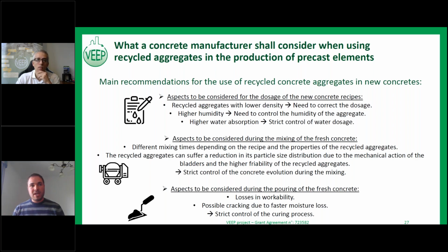In the second stage, we have to consider some differences during the mixing of the fresh concrete. The mixing time is not the same as for a natural one. Normally we have to mix more time, but we have to pay attention that if we mix more time, we can reduce the particle size distribution of the recycled aggregate because they are more friable than the natural one. So we have to have a strict control of the concrete evolution.